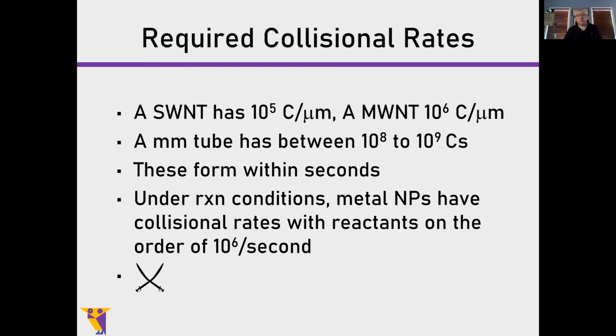Typically, if you measure some times, you'll find that a nanotube that long forms in about a second or two. But if you go back to your Castellan and you dig out your equations on kinetic theory and calculate the collisional rates between the reactants and the metal nanoparticles at these pressures, you'll find that the collisional rates are on the order of 10 to the 6th a second, or about probably 100 to 1,000 times too slow.